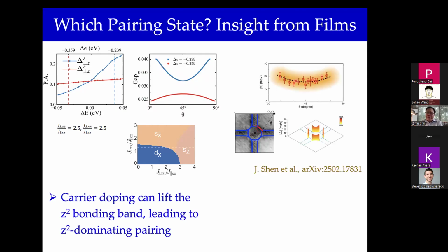And there are some recent experiments, not too recent, showing that at least in that particular film, the gap varies in a way that's compatible with extended S-wave and with the dominant pairing associated with the dz-square orbitals. This is the Fermi surface characterization. So 45 degrees is the diagonal, and the variation is shown in this span. How much this says about whether the bonding 3dz-square states are crossing the Fermi energy in that particular film is a bit indirect, but it does give some hint for that part of the physics.